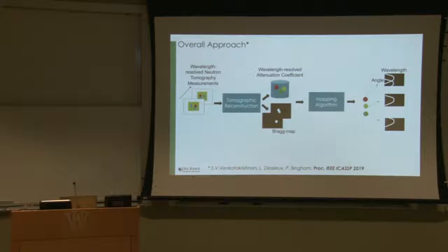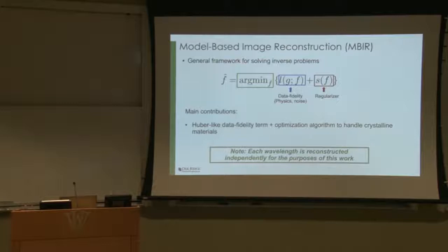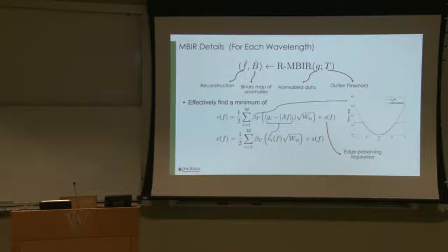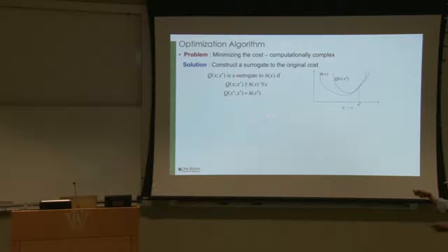So I'll go into some details now of how we do the CT tomographic reconstructions when you have data not corrupted, but affected by Bragg scatter. So the main idea is to, again, think about the model-based reconstruction framework, and we're going to come up with a new data-fitting model here to handle the fact that some of the measurements were affected by Bragg scatter. So the main idea here is that we're going to design a method that takes the noisy data, it's going to have some parameter which controls which measurements were bad, and then come up with a reconstruction. And that's the cost function that we have designed is a sum over all the measurements of some penalty, which I call the Huber-like penalty, applied to each measurement.